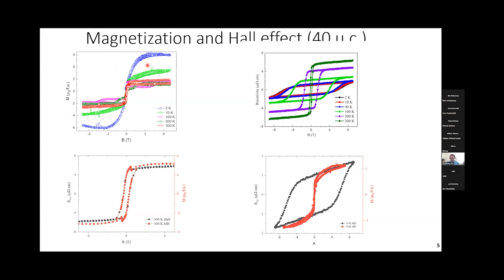The saturated magnetization shows a decrease from 2 Kelvin to about 100 Kelvin, and then increases a little bit from 100 to 300. The hysteresis loops measured in the Hall and the magnetization are quite different. We compared them here. We can see at 300, the Hall and the magnetization loops seem to coincide with each other. But if we lower the temperature, we can see it's quite different. This is very hard to explain by a simple ferro or ferrimagnetic order.